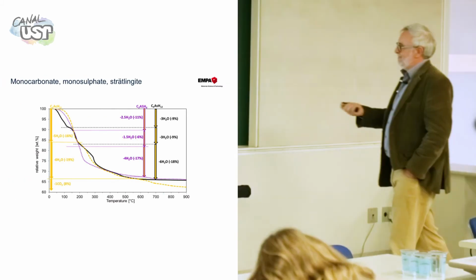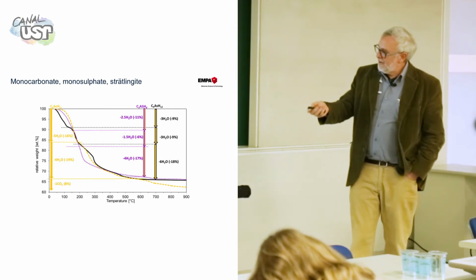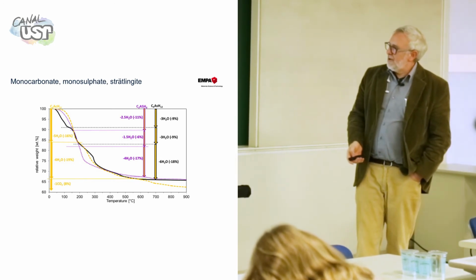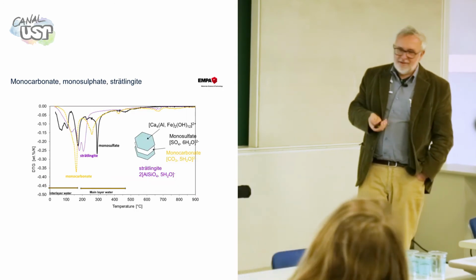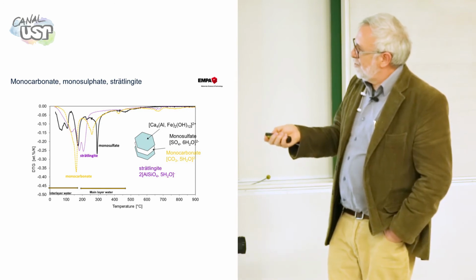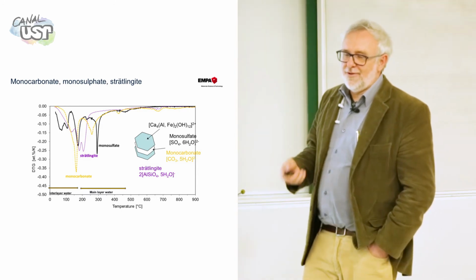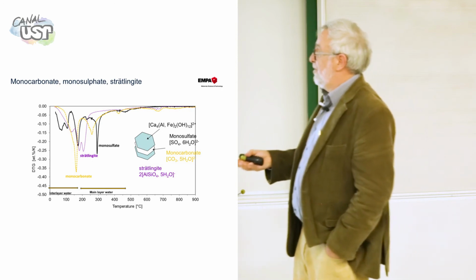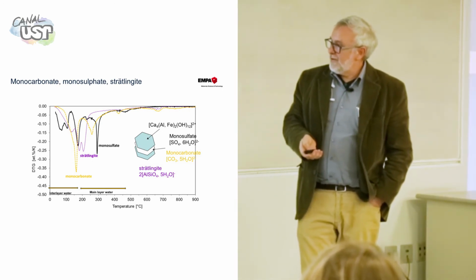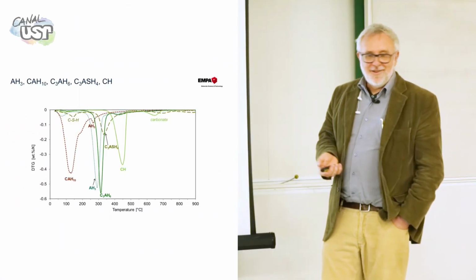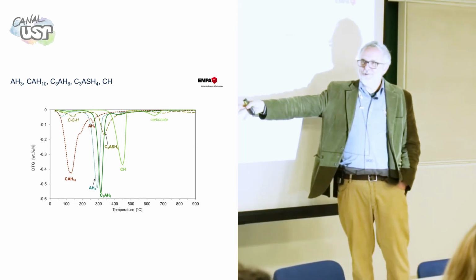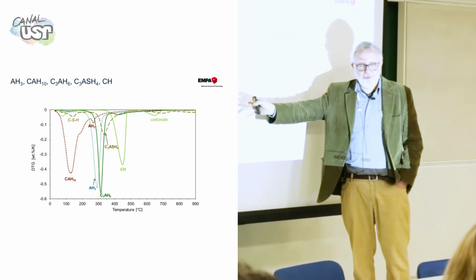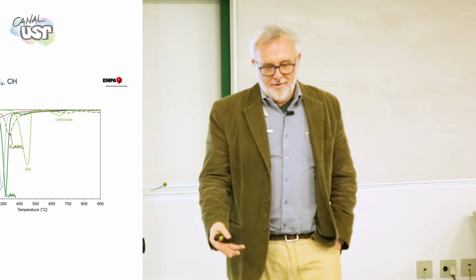Monocarbonate, monosulfate, stratlingite. This is a mixture. You see different peaks here, you can more or less cut between them. But actually the peaks are like that. You see the reactions in each step, but this same reaction occurs in the three phases. So you will never know which one is going to be decomposed at a given temperature, because they are the same variety and same things, and they are intermixed. So these are the derivatives of everything you saw so far. Weight loss is the integration of all these curves, considering the mass presence of each one, which we don't know clearly. We can do thermodynamic simulation to have more or less an idea of how much we have from each one, but that's a different scenario.